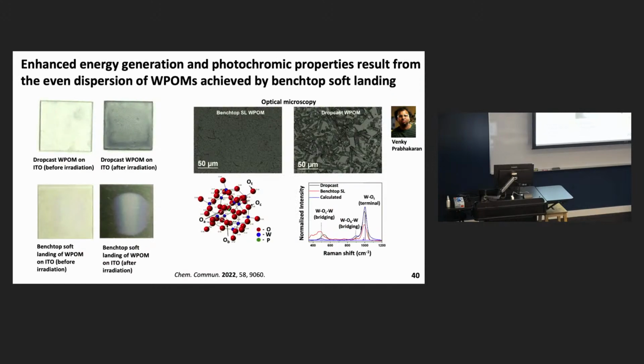Another thing that was interesting about this material is these polyoxometalates are photochromic, meaning that when you shine light on them, they change color. So there's potential applications for this in things like smart windows, basically, that once they're irradiated, they turn opaque, so they stop light from entering and heating the building. On the left-hand side, you can see a drop cast version before and after irradiation. On the bottom, you can see one created with benchtop soft landing. And in this case, we didn't even need electron microscopy. We could really see the difference in morphology just using a conventional optical microscope. You can see there's a finer dispersion of the soft-landed species, whereas the drop cast forms these large aggregates, where a lot of the material is essentially wasted in the center and doesn't interact with the substrate. So this was recently featured on the cover of Chemical Communications.